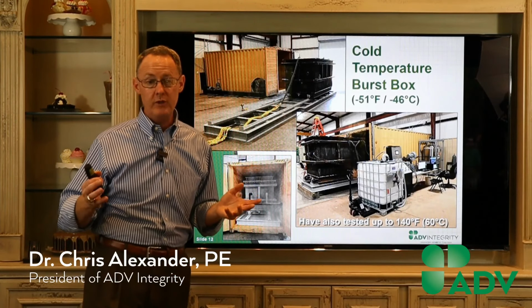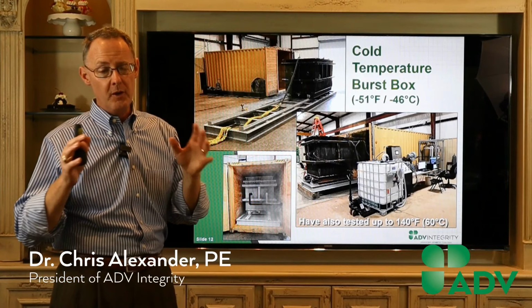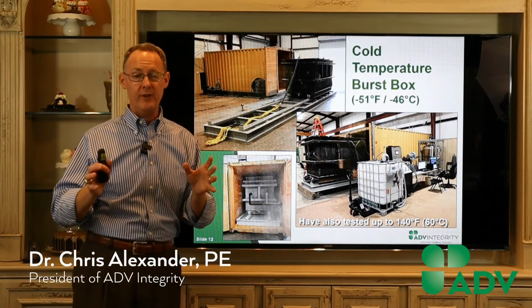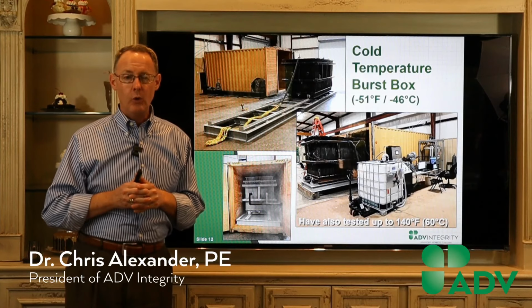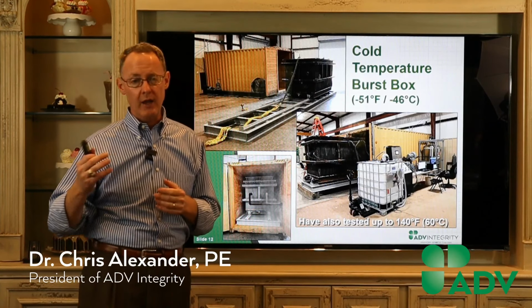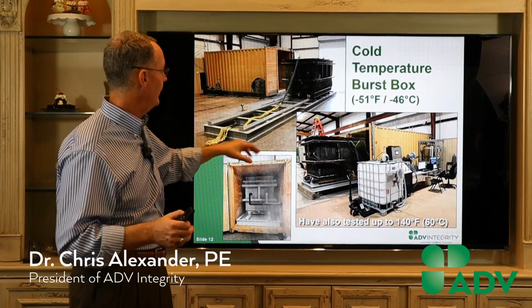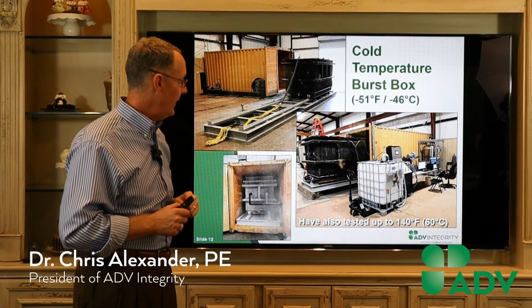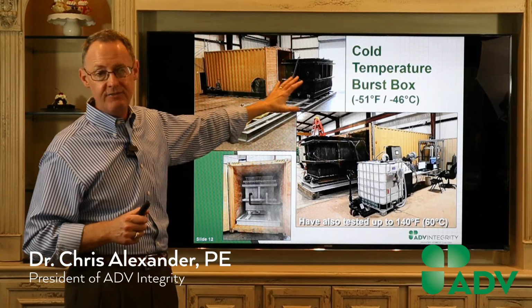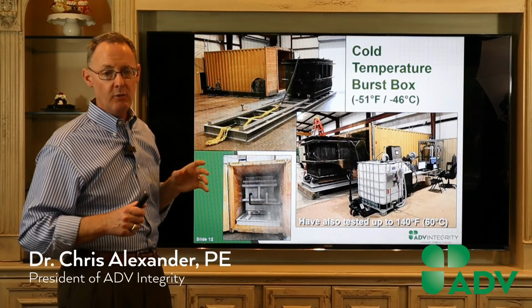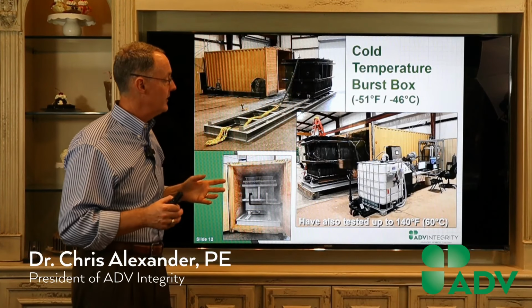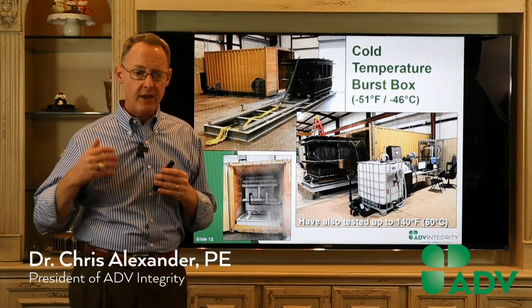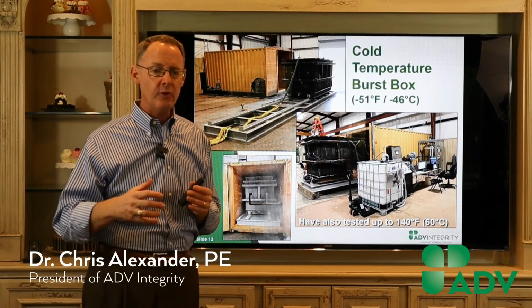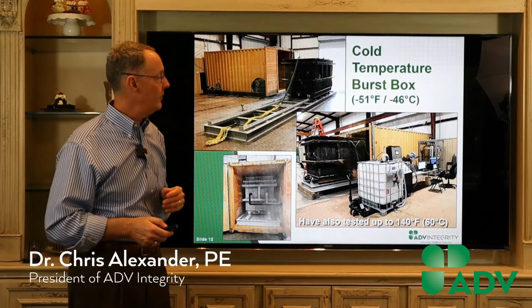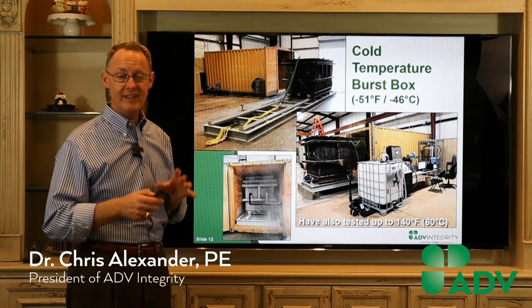Some of the other things that we do, those of you that are familiar with ADV, we do a lot of work in the composite space. And so we'll do cold temperature things, we'll do elevated temperature. So we actually built a box, Corey designed it for us, and we did a pressure test down to minus 51 degrees Fahrenheit. So very cold temperature. We've also done some composite work all the way up to 60 C or 140 F. So we've got the ability to simulate different environments. So it's nice to be able to do that. It takes a lot of work to get to that point.